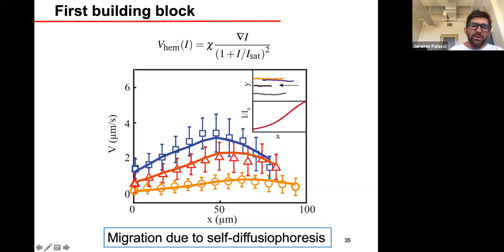We repeat the experiment. The symbols are the experiment, and the solid lines are the prediction we have for the hematite speed, with two parameters for those three curves. So bottom line, we can describe all our experimental data for different types of light gradient with only two parameters. And that shows that diffusiophoresis is really the important thing to get our particles to move. That's what I want to get through this slide.